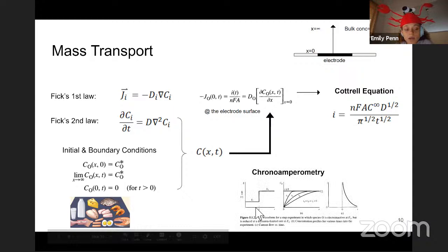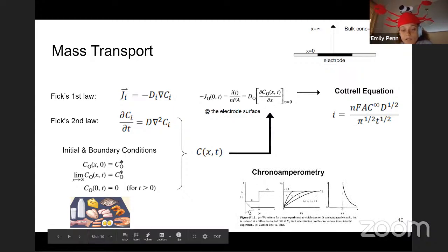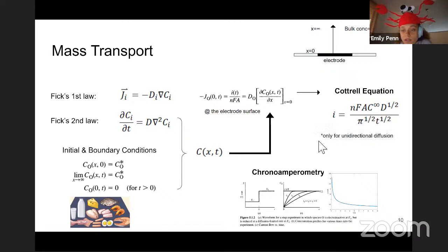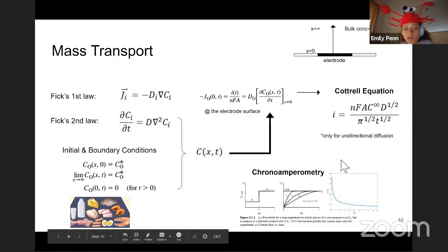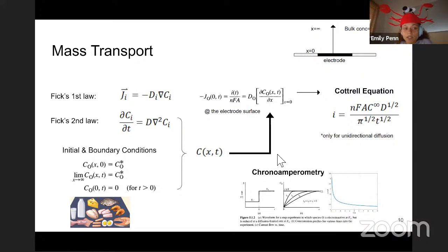So this describes the current as a function of time. This equation you've probably seen before for chronoamperometry. So if we apply a potential step, we can look at the concentration change over time, and the current will follow a t to the minus 1/2 function. It's important to note that the Cottrell equation only applies for unidirectional diffusion. So in this example, we were considering just diffusion in the x direction. But this is valid for a case where you have a planar electrode. And this equation is useful for chronoamperometry, and it can also be used to look at CV after the peak.